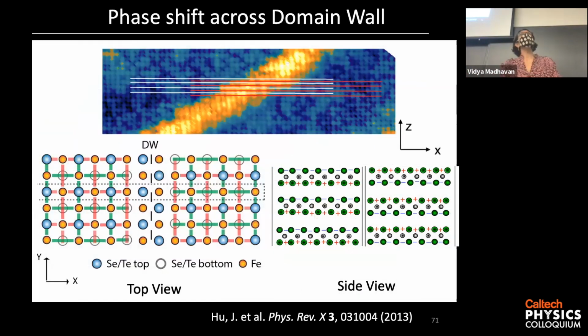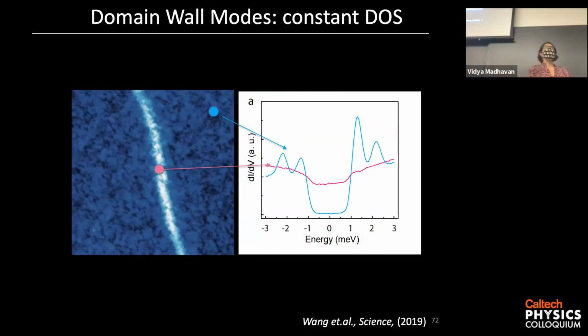Okay, so now let's ask, what do we see at the domain wall? Okay, so this is what we see. So far away from the domain wall, this is the blue dot. You see the superconducting gap. This is zero density of states. At the domain wall, you see finite density of states inside the superconducting gap. But more remarkably, this is really interesting, it's flat, meaning that the density of states has no features. There are no peaks, nothing. The density of states is flat.